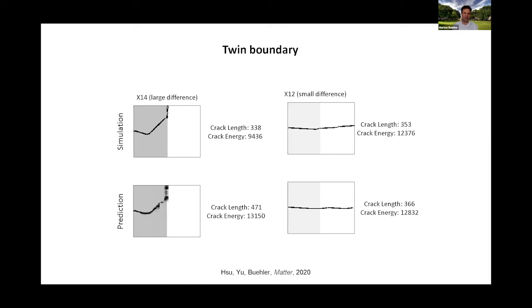And we've been able to simulate this using molecular dynamics. So we went back and we actually simulated this system using full atomistic simulations and show that the machine learning prediction, which has never seen a situation like this, agrees actually with the prediction from the MD simulation, which is the ground truth. So that's really simulating the physics of every single atom.